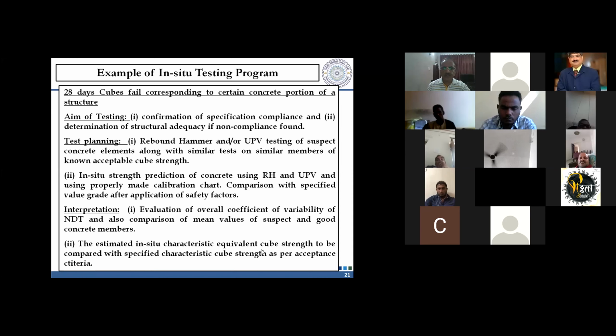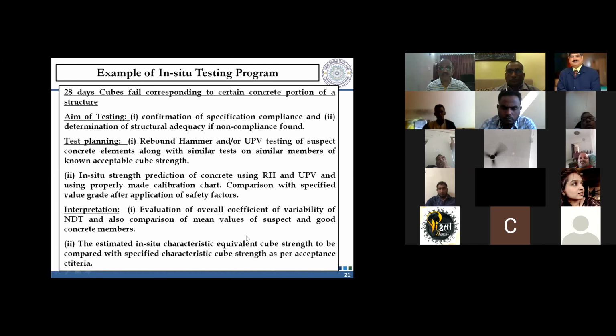But in the second case, you have found the strength of the concrete, fck, also. Compare the fck with the fck specified, following the acceptance criteria explained to you in the 2-3 slides back. If it is accepting that criteria, you can say that everything is fine. If not, you will say that this concrete is suspect. There is a problem, and then you will recommend further testing. Further testing means cores can be extracted from the suspect area.